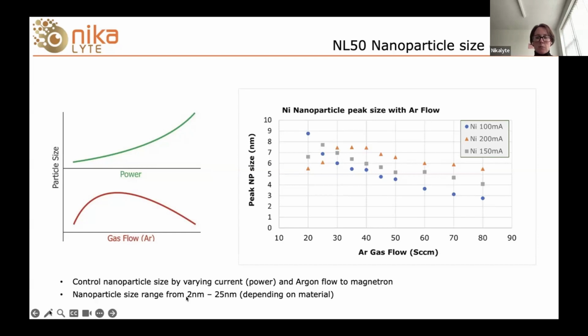In general, we can produce nanoparticles with the NL50 in the range of sizes of 2 to 25 nanometers. I put in brackets that this depends on material, because you can see here that for these nickel nanoparticles, we're not getting up to those sizes. It really depends on the material. Some materials form nanoparticles very easily, including larger nanoparticles. Other materials, such as platinum, which is a very good example, like to form small nanoparticles, so tend to be closer to 2 to 10 nanometers.